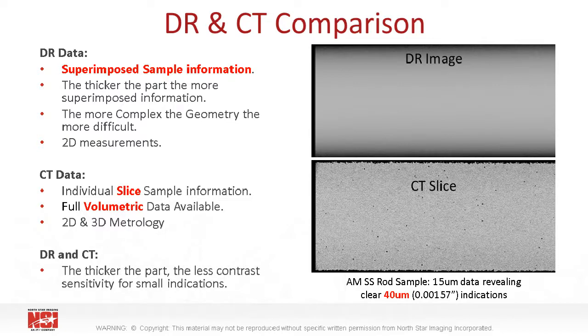even though the DR image was one of them used to generate that slice information. Basically what's going on is we have all of this superimposed information, and the thicker the part, the more superimposed information you have, so the more difficult it is to generate the contrast sensitivity that you see in the bottom slice. With the DR data, you can do 2D measurements. The CT data, we can slice through the part back and forth in a direction and then generate volumetric data as well as 2D and 3D metrology. In DR and CT, the thicker the part, the less contrast sensitivity you have for smaller indications.